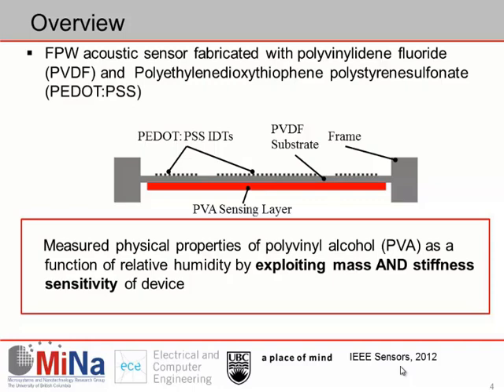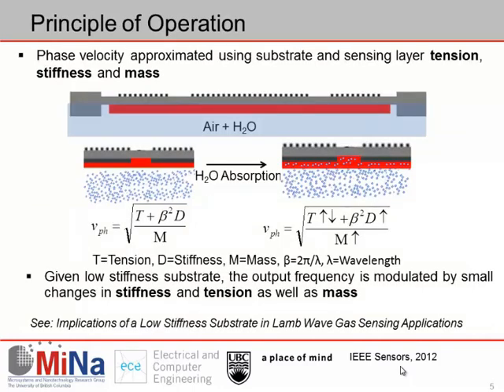So just a bit of detail about the picture here. We have three sets of IDTs, one transmitting, two receiving, a drop-cast PVA sensing layer, and the PVDF substrate. As I mentioned earlier, the flexural plate wave velocity and frequency, which we are trying to measure to detect something about the sensing layer, is determined by the physical properties of both the sensing layer and the substrate. Using Kirchhoff's plate theory, we can approximate the phase velocity of this wave with this relation here, the phase velocity of the fundamental antisymmetric plate wave. This is phase velocity as a function of tension, of both the sensing layer and the substrate, stiffness, and mass.